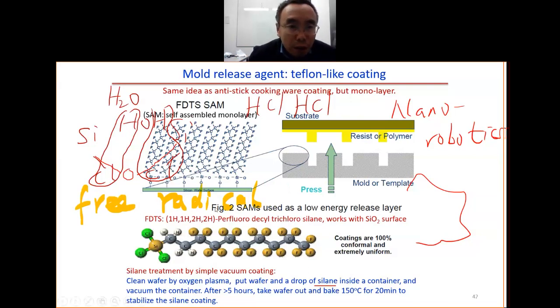We have lots of free radicals. But we know that free radicals are very reactive. Those free radicals will damage this self-assembled monolayer. As a result, after maybe 10 imprints, you need to coat the self-assembled monolayer again. Because of the free radicals, when you do the UV imprint, you generate a lot of free radical polymerization. This is not good for this one.